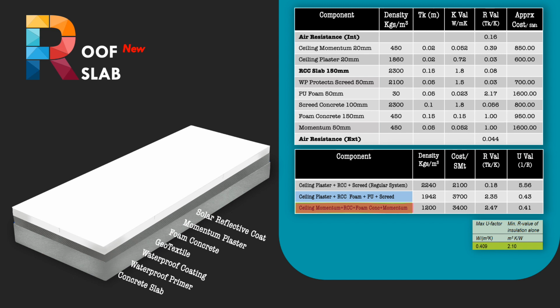System 3 is as per our recommended cross-section on the left. R value of our recommended system is 2.47 and U value 0.41, which matches the recommended standards. This system is fully cementitious, hence ensures excellent bonding between layers. Protection screed over waterproof coating is not considered, since foam concrete is a pour and fill process, and does not